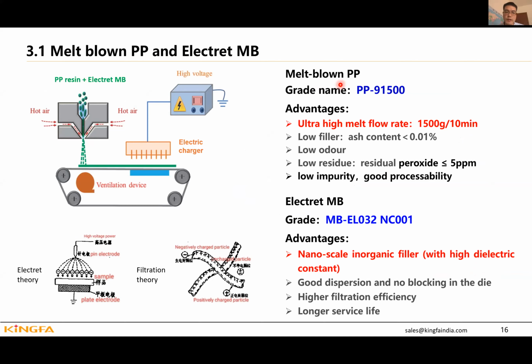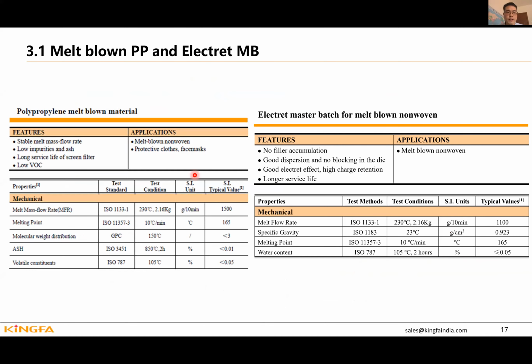Besides the meltblown PP, we need to add some electret master batch. Why do we need to add this one? Because for PP, the dielectric constant is very low. That means if we put an electric charge in this fiber, we cannot get very much static electricity. So we need to add some nanoscale inorganic filler. This filler has a very high dielectric constant, which means it can capture more static electricity, and it can be used for a long time. So that's why we need to add this electret master batch together with the meltblown PP in this production. Here is some TDS of Kingfa material for the meltblown PP and the electret master batch.